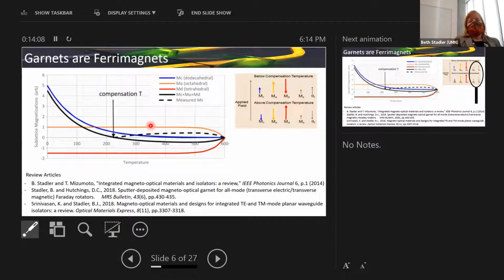So if there's two octahedral iron for every three tetrahedral iron, which is what that composition gives you, it means when your dodecahedral site hits 1, you've got 1 plus 2 equals 3. So your net moment is now 0. And then after that, your net moment would become negative, but you don't really ever measure a negative magnetic moment. So what you'll end up measuring is this bounce right at the compensation temperature.